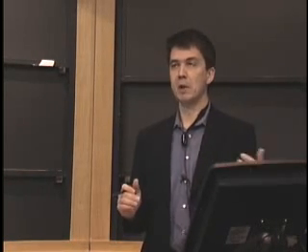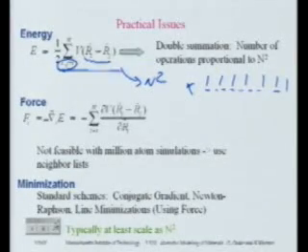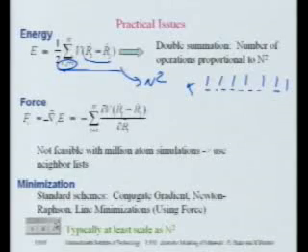And people do tricks. If you have millions and millions of atoms in your simulation, if you know ahead of time that some of them are very far from the atom on which you want to calculate energies or forces, then you really never want to look for their distance. So people do things like keeping neighbor lists. Literally, for every atom, you would know these other atoms are possibly in its neighbor environment. Okay? So then you really only have to look for distances with those atoms.